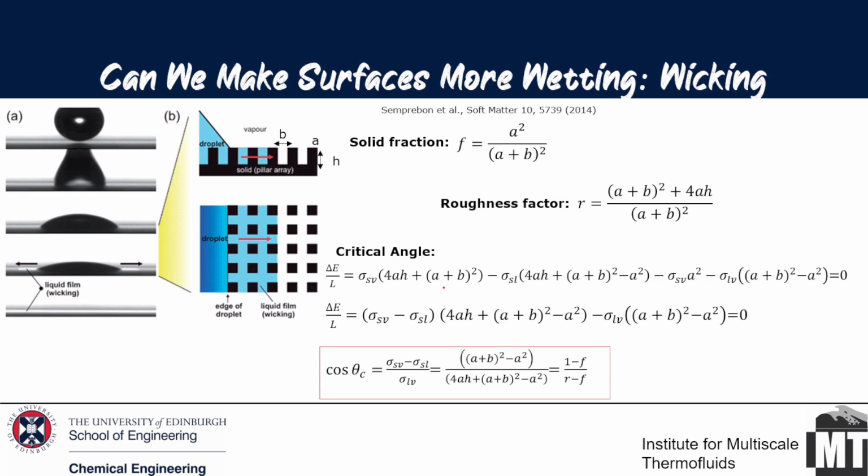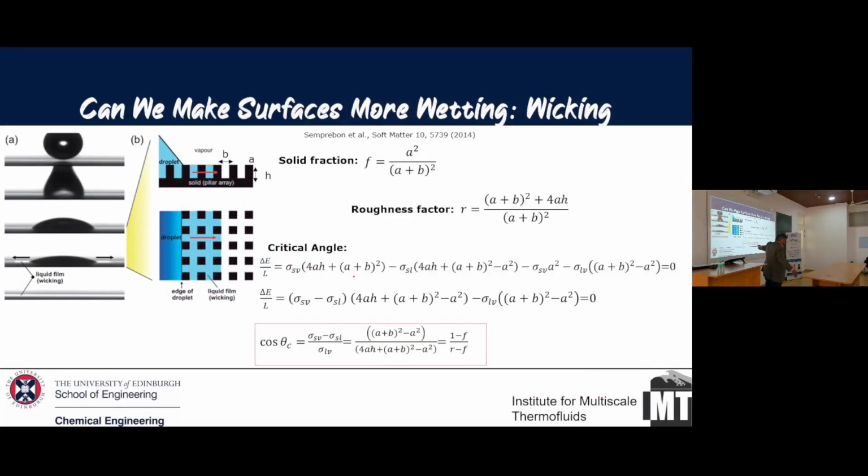But what I have done, you can see the notes yourself, is I've tried to bring together the energy physics just by looking at the pattern of the substrate. It's based totally on the geometry parameters, nothing else. So basically, it's energy minimization, looking at the energy of the substrate based on the surface geometry. I define a certain fraction, I define a certain roughness, and based on that, I calculate the so-called expected contact angle.